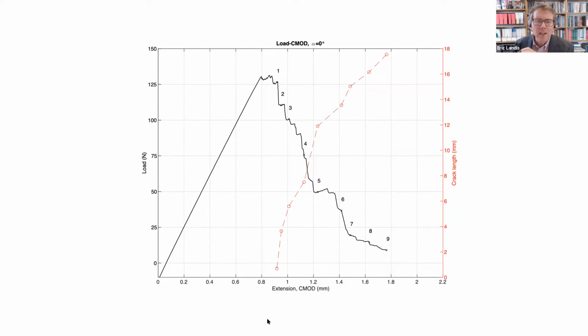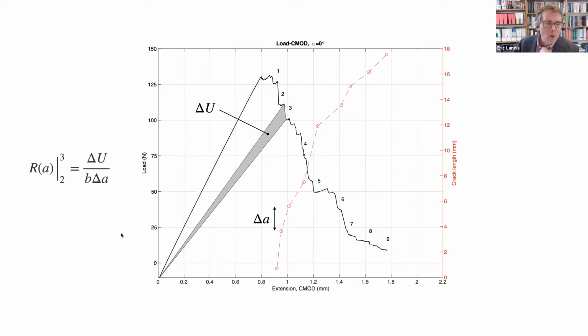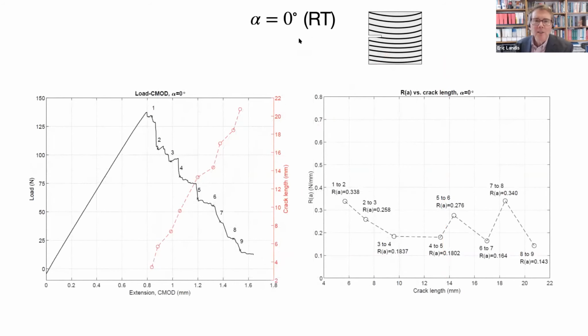Now for our crack resistance, we're interested in, as best we can, incremental crack resistance. So over a range between two different points, in this case between 2 and 3, we will measure the change in the dissipated energy, and then the corresponding crack growth over that range. And we just say that the crack resistance is simply the energy divided by the crack area, which is the crack length times the specimen thickness. So the first result I'll show is an angle of 0. So now the crack is propagating in the radial direction. And again, what we see is relatively stable crack growth, a fairly stable descent in the load CMOD curve, and a relatively straight crack growth.